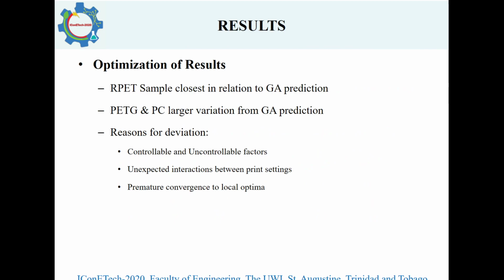This deviation may be attributed to the GA's inability to account for all uncontrollable or controllable factors that impacted the sample strength. There may have been some unexpected interactions between print settings not considered in the design of experiments that also affected the flexural strength of the samples. There may also have been some premature convergence to local optima, which caused the GA to stop simulating before a true optimal value was found. These issues may have been resolved if extensive work was done in testing and selecting optimal input settings for the GA to suit the data being examined. This should then be considered when doing future research using genetic algorithms or any other evolutionary method to determining optimal parameters.